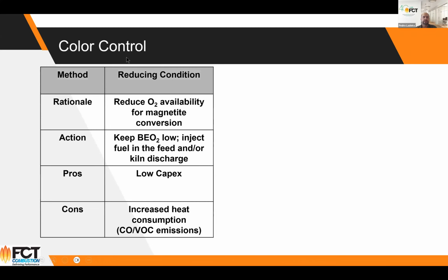So looking at the color control methods available, one of them is just keeping the kiln in reducing conditions. The rationale here is to reduce the oxygen availability, to try and convert to magnetite and to keep magnetite as such, which tends to be darker and less red. You try to keep the back-end oxygen low by physically controlling the kiln, but also injecting fuel in the feed or even in the kiln discharge. So by adding fuel, you can have a localized reducing condition, and you can probably get a dark color, avoiding the pink or the red.